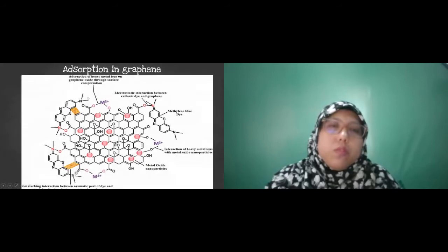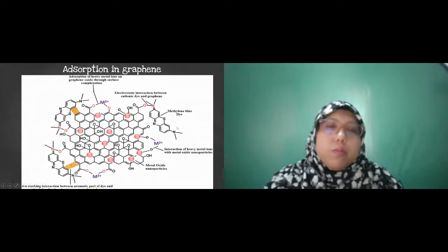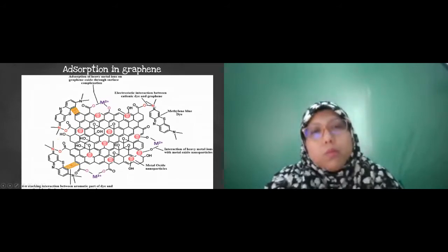Now, the same adsorption when we tried with graphene or graphene oxide. Here is a schematic for graphene oxide. Here you see the graphene already has some functional groups, and here is a methylene blue dye molecule. These functional groups get attached to this dye, and that's how it is adsorbed. This is not in a pore. So this graphene adsorption is very quick compared to carbon, very quick and very efficient, but maybe this cannot hold the large molecules for long. So this can reverse back to the water. But the amount of graphene required for adsorption and the time it requires for adsorption is amazing.